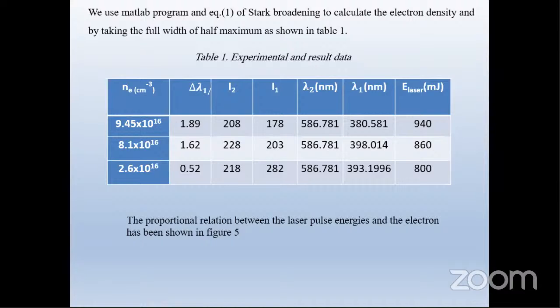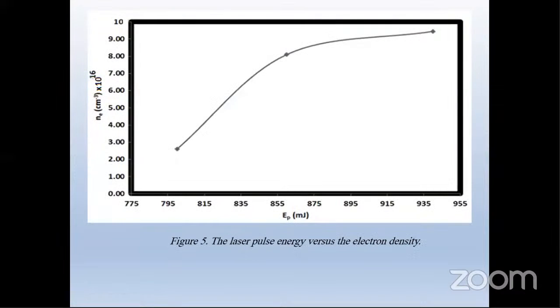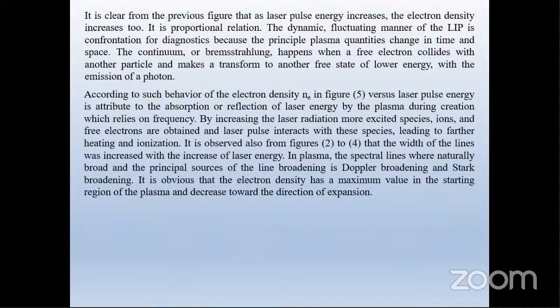As we observe, as NE increases, or as energy of the laser pulse increases, the electron number density increases also. This figure 5 shows the laser pulse energy versus the electron density. It's clear from figure 5 that as laser pulse energy increases, electron density increases too.